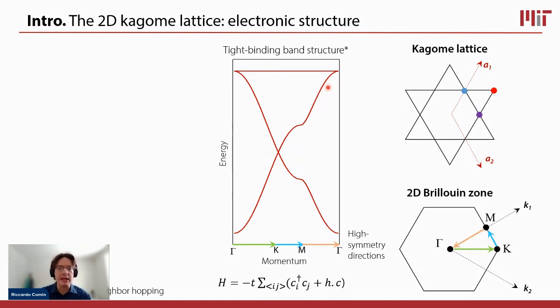This is from a simple tight binding, assuming only nearest neighbor hopping, meaning the electrons only hop on a nearest neighbor bond. And so there are 3 main features to this band structure. One is the presence of Dirac fermions. So basically massless fermions that exist around the K point. Only around the K point you have these bands that are crossing each other linearly. So they have, at least in the limit of looking around the K point, 0 mass.